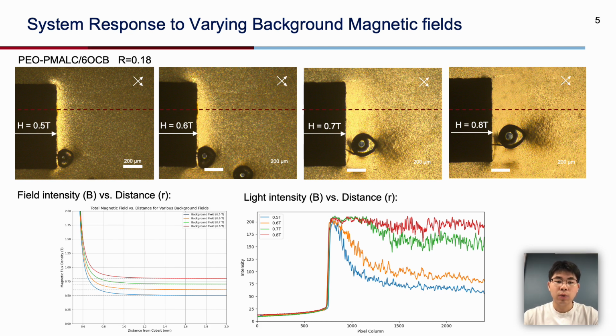We also investigate how the system will respond to varying background magnetic field. We can see as we increase the background magnetic field, the bright region becomes broader and broader, which aligns with our expectation. So we can imagine the alignment is actually the competition between the magnetostatic energy and thermal energy. So the bright region is actually the place where magnetostatic energy is much larger than kT. And as we increase background magnetic field, the bright region will become wider and wider.